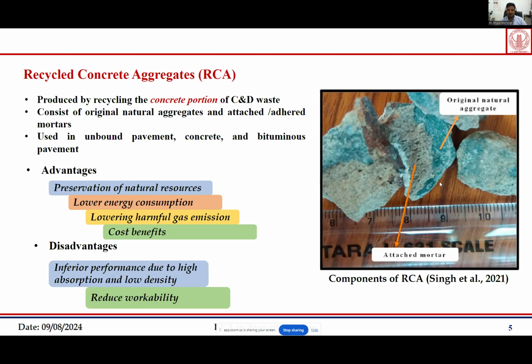But what are the disadvantages? The major disadvantage which comes in recycled concrete aggregate is because of this layer of adhered mortar which is attached to the aggregates. Because of this layer, it forms not a very strong bond with the aggregate. So when the load comes over it, it breaks down, and then that reduces the overall strength of the mix. It has higher water absorption also, and it reduces the aggregates' specific gravity also.